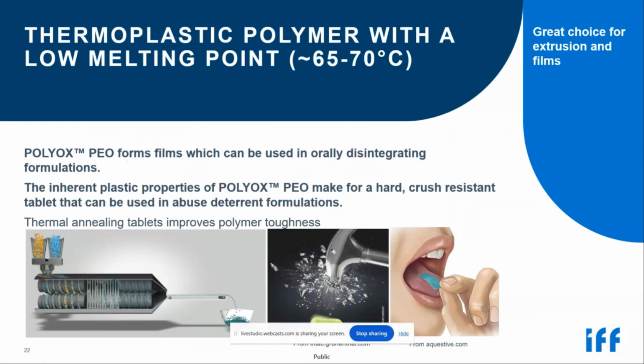The thermoplastic nature of the polymer, along with the fact that it's inherently tough, makes it ideal for abuse deterrence. In this case, we're talking about thermally curing a tablet of PEO, which essentially fuses the tiny tough particles together into one tough large particle or tablet that's hard to crush and hard to grind.